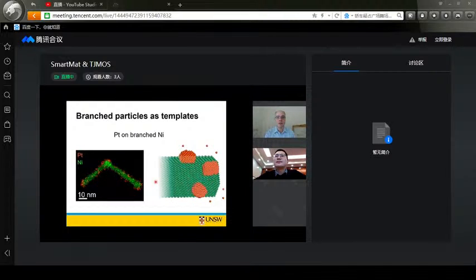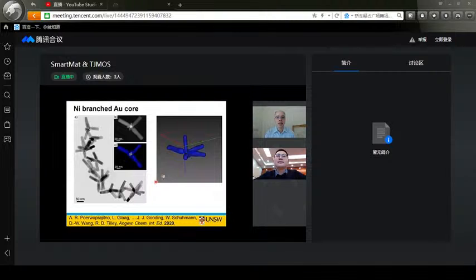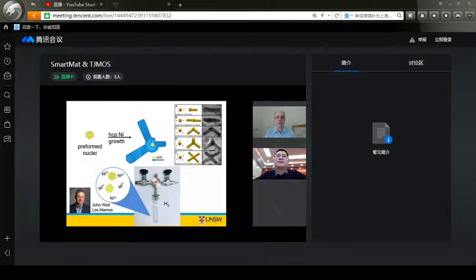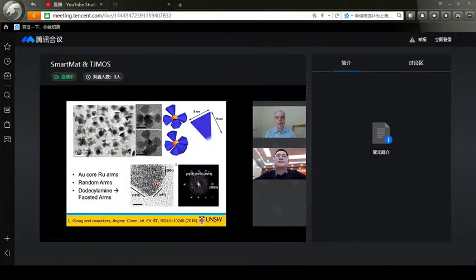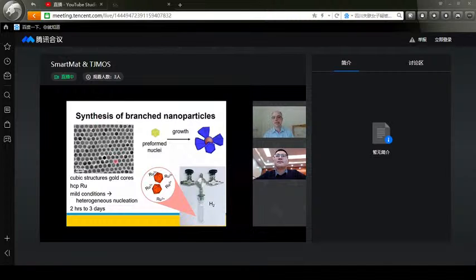And the other thing that we do deliberately is when we're doing these seeded reactions, we tend to prefer to use gold seeds, because the nice thing about gold is that it doesn't oxidize. So you always have a clean metal surface when you're growing the next metal on top. Whereas if you use something like silver, sometimes you can get a bit of an oxide layer, and then the next metal doesn't want to grow on top as much. Okay, so those are some of our thoughts.